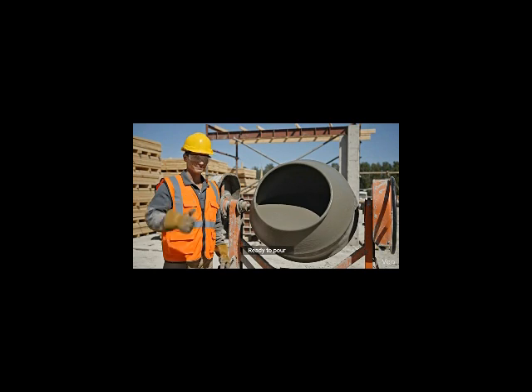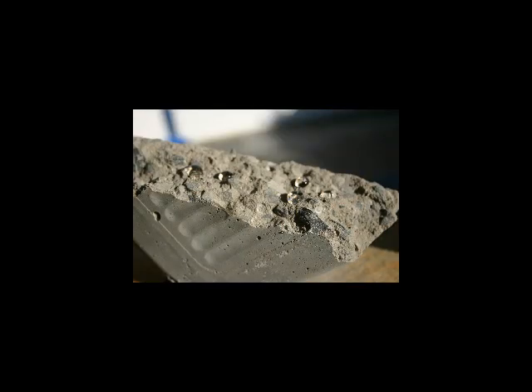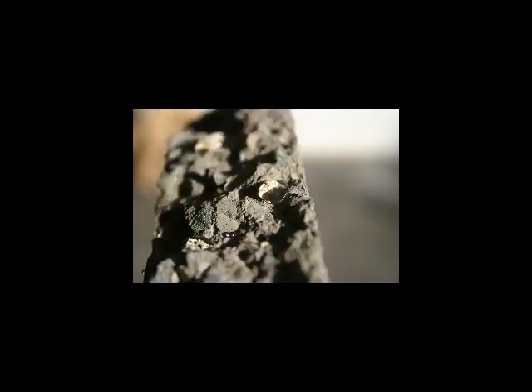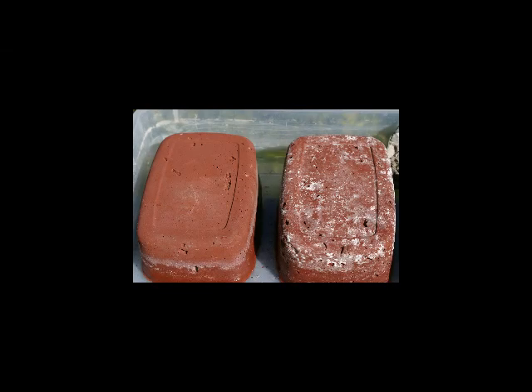After the mix is cured, your concrete, render, or tile screed will be permanently water repellent. You can easily see and test the results yourself. First, we test the integral water repellency. A cross-section of the cured concrete sample demonstrates the depth of protection. By breaking the sample in half, we can see that the 3001 hydrophobic agent provides integral water repellency throughout the entire matrix, not just on the surface.